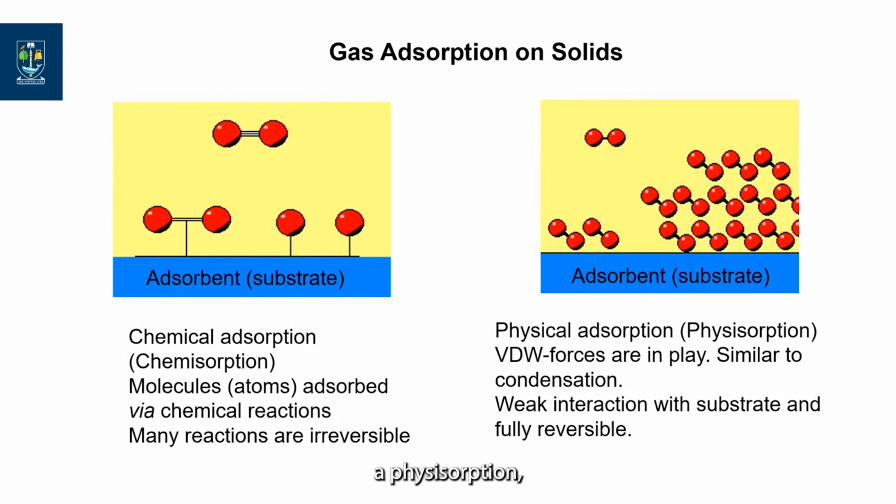In the case of physisorption, as the name suggests, there are only physical, weak van der Waals forces at play. The interactions between the surface and the adsorbing gas or liquid are very weak. They are of low enthalpy, typically just a few kilojoules per mole. That makes physisorption an interesting process for studying porous materials, as it's a fully reversible and non-invasive process. You can measure it as many times as you want, and no damage is made to the material during the measurements.